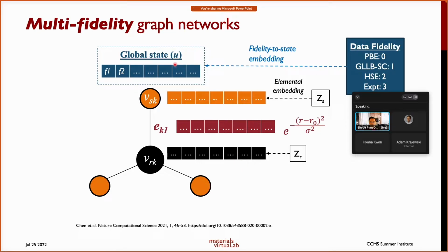So remember, when I talked about the architecture of the materials graph network, we have something called the global state, right? And the global state applies to the entire graph network. And initially, we use this global state as a way of embedding properties that apply to the system as a whole, things like the temperature and the pressure. What we realized is that this global state can also be used to embed data fidelity, right? So for example, if we assign a fidelity level, let's say PBE is 0, HSE is 2, experimental is 3, and we embed that fidelity in this length 16 vector,